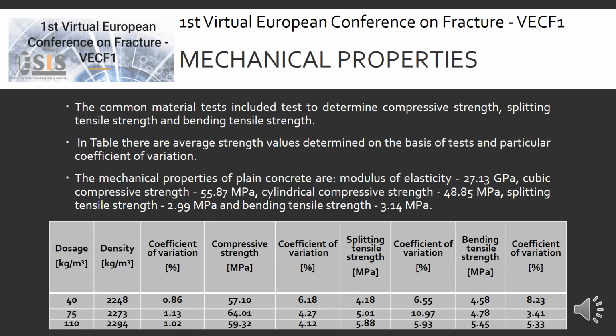The mechanical properties of plain concrete are: modulus of elasticity 27.1 gigapascals, cubic compressive strength 55.87 megapascals, cylindrical compressive strength 48.85 megapascals, splitting tensile strength 2.99 megapascals, and bending tensile strength 3.14 megapascals.